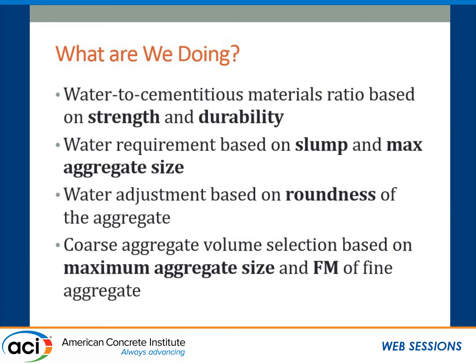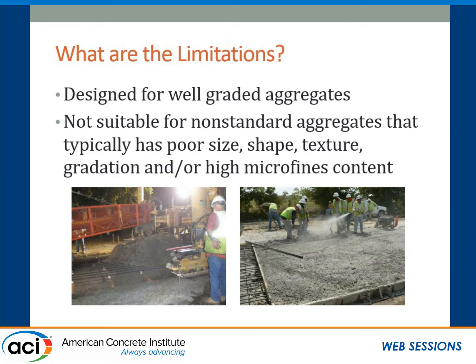This ACI-211 method works pretty well for any ASTM-C33 aggregate, but it becomes a problem when the aggregate doesn't meet ASTM-C33 requirement. Our group was involved a couple of years ago in one of the paving projects in Dallas-Fort Worth, where they were trying to introduce a manufactured sand which typically has poor size, shape, and gradation as well as high micro-fine content, and the result was horrible. They used ACI-211 method without any adjustment for poor size, shape, gradation, and high micro-fine content, and the workability was very poor. You can see from the photograph that it's very difficult to spread that concrete, and in a second photograph they're spraying additional water to get an acceptable pavement finish.